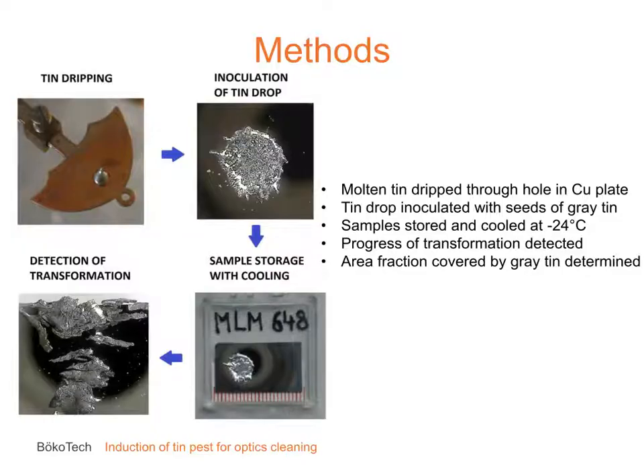In my experiment, molten tin is dripped through a hole in a copper plate. At some distance below, the drop falls on a metal plate or on a multi-layer coated mirror. The splash is then inoculated with seeds of gray tin. Samples are stored in transparent containers in a refrigerator at minus 24 degrees. The progress of transformation of gray tin is examined periodically using a CCD camera or a microscope. The area fraction covered by gray tin is then determined. To increase the conversion rate, in some cases the drops are also deformed or the surface oxide layer is removed.